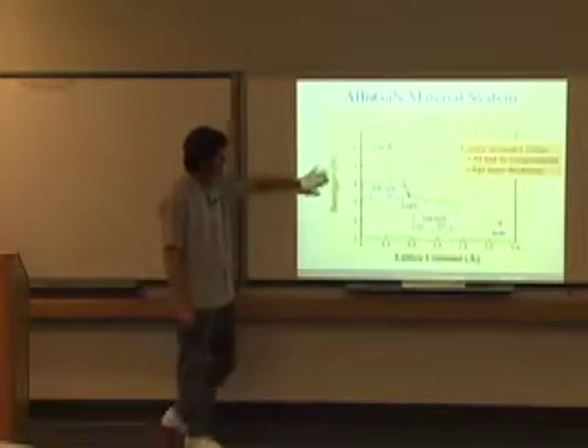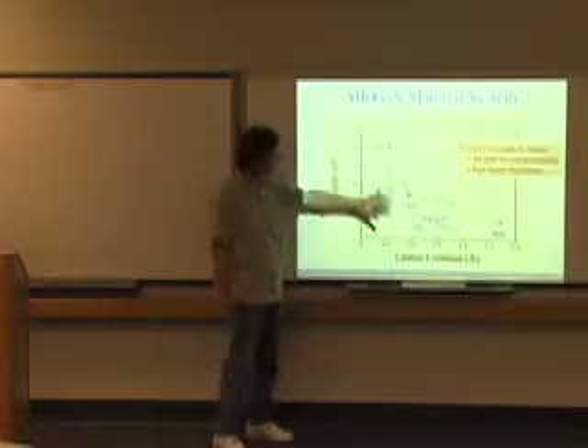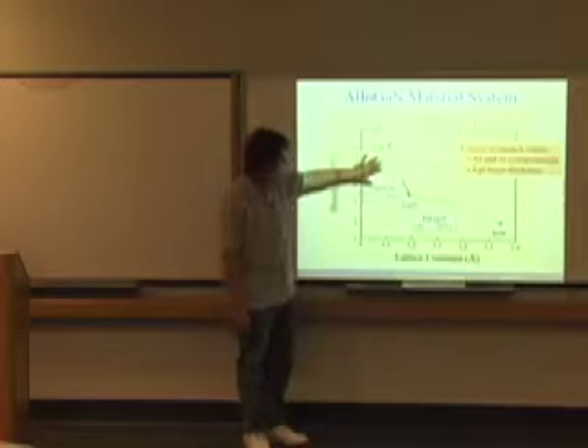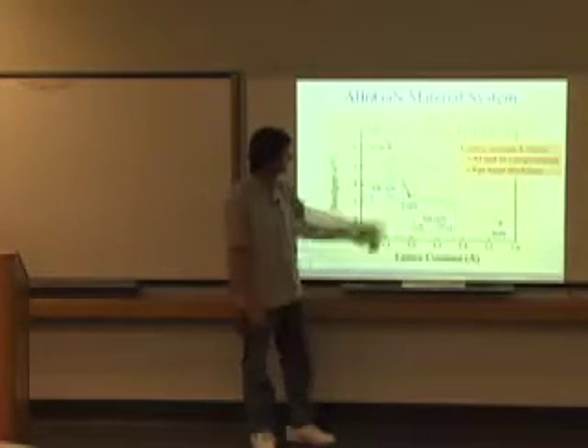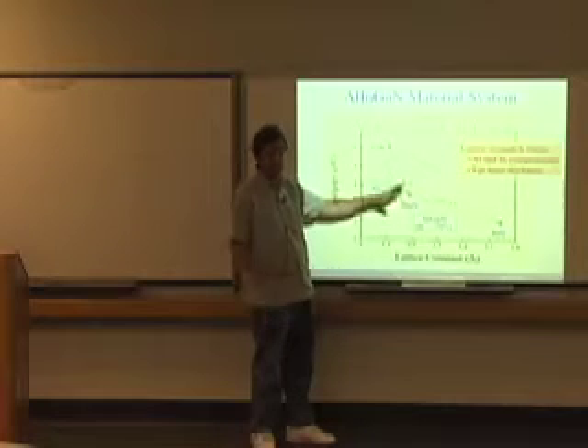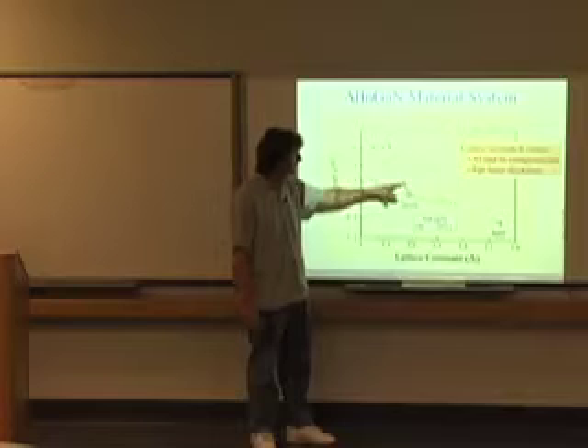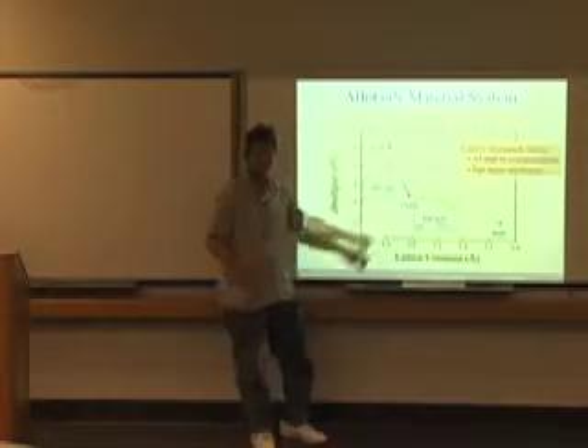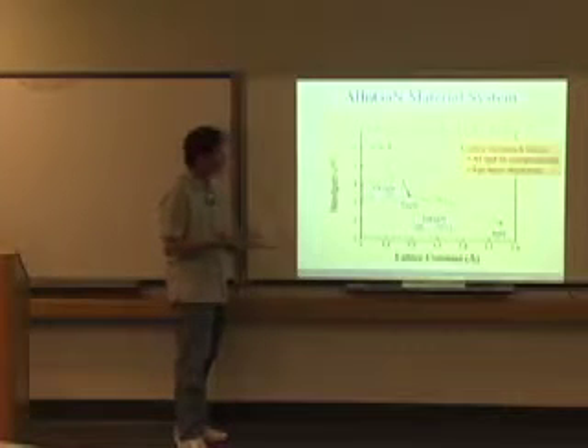When you look at the Al-InGaN material system, if you look at the band gap as a function of lattice constant, you see that it's a lattice mismatch system. Aluminum nitride has a smaller lattice constant, indium nitride has a much larger lattice constant. And so if you want to try and go to higher band gap cladding layers and you want to follow the ternary AlGaN, you have no choice but to put strain in the material relative to gallium nitride, which is something that's different than you have with gallium arsenide or even InGaN.